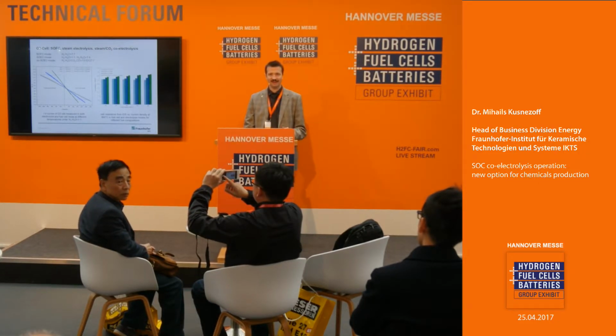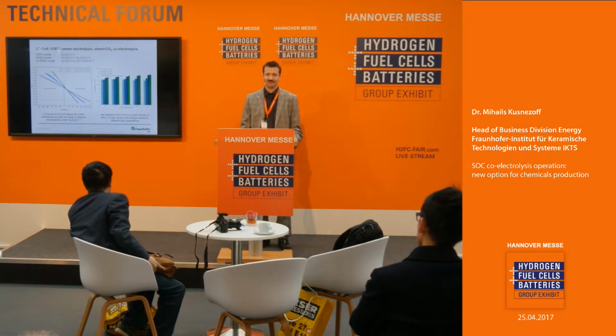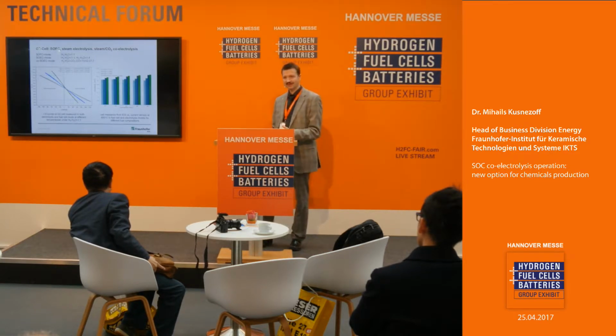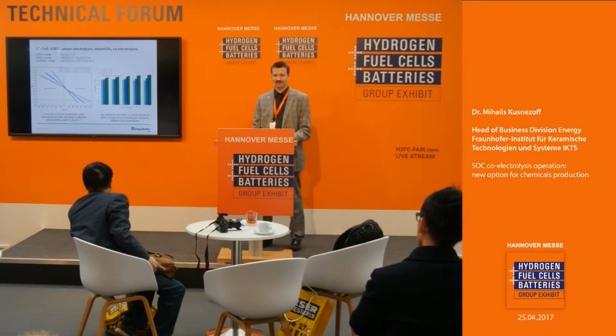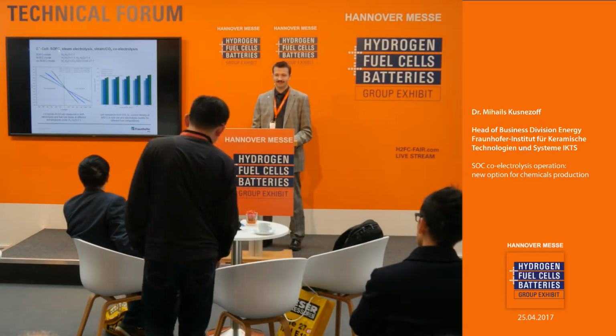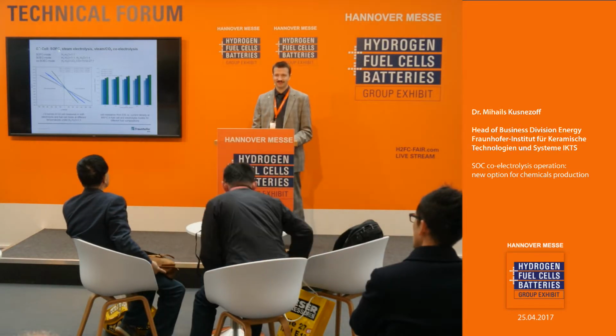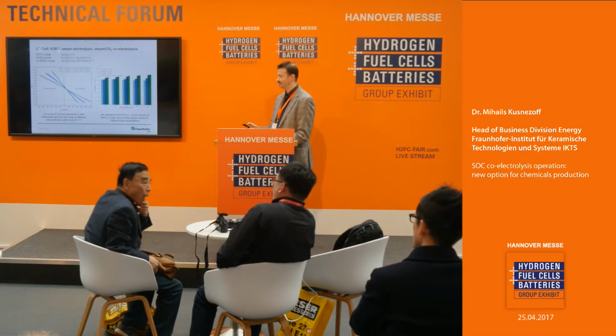But if we analyze it using impedance spectroscopy, then we see that if we move from SOFC operation to electrolysis operation, steam electrolysis or co-electrolysis, then we see some increase of impedance, and we have justified that it is connected with ohmic losses and with some diffusion losses in the fuel electrode.